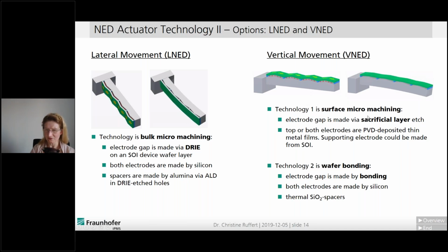One is surface micromachining. In this case, the electrode gap is made by sacrificial layer etch. So we have a sacrificial layer in between the upper and bottom electrode. And in this case, top or even both electrodes are made by physical vapor deposition of thin metal films. And the supporting electrode could also be made from silicon on insulator.